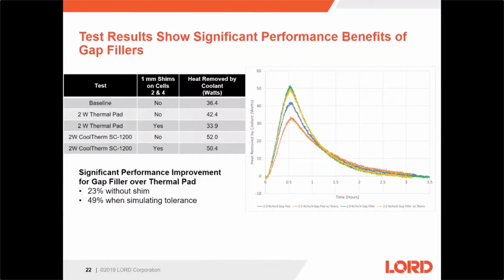The rightmost column in the table displays the amount of heat removed by the coolant, and as you can see, in both instances, the gap filler removed over 50 watts from the assembly, whereas the thermal pad did not. The gap filler without the shim removed 23% more heat than the thermal pad in the same setup, and removed 49% more heat than the thermal pad when the shim was included.